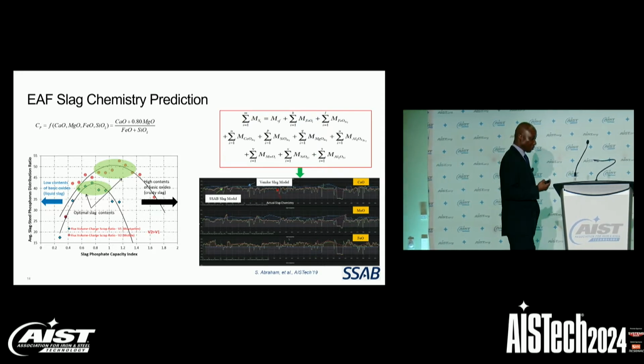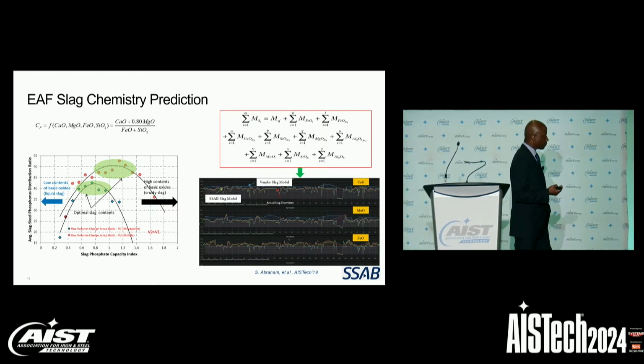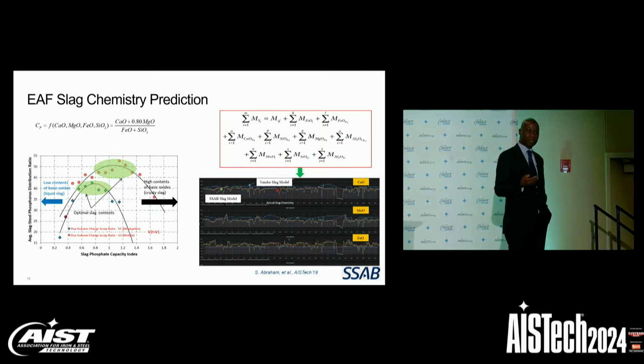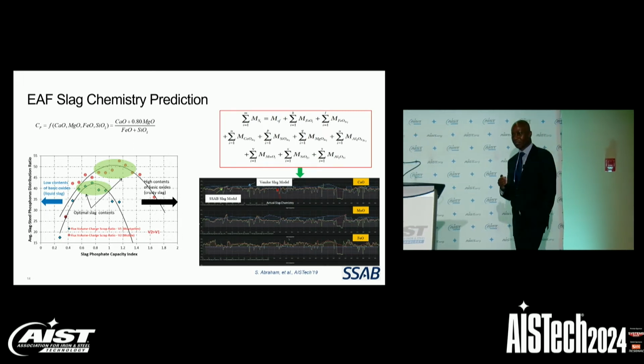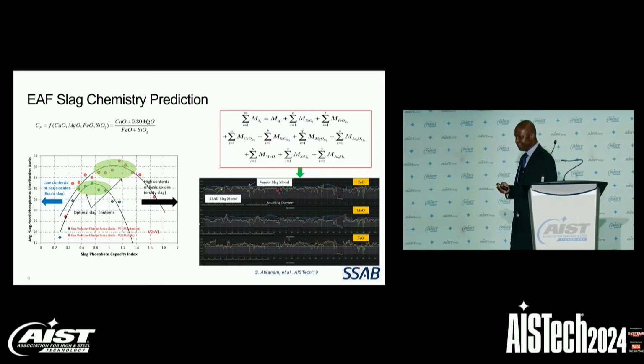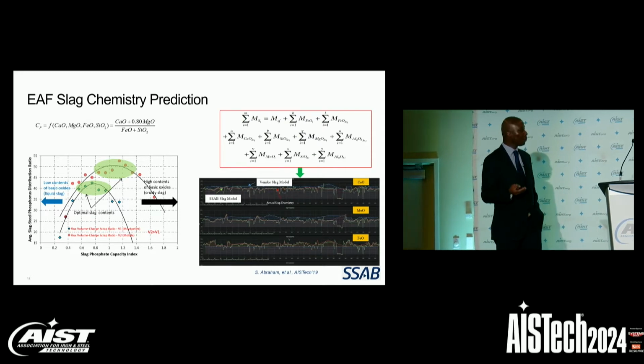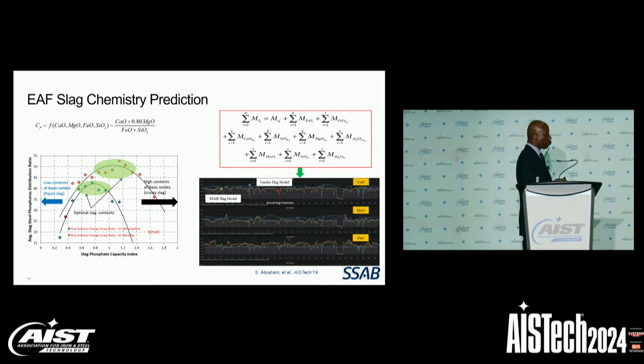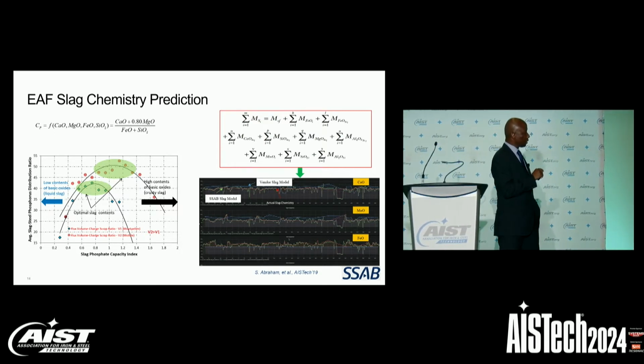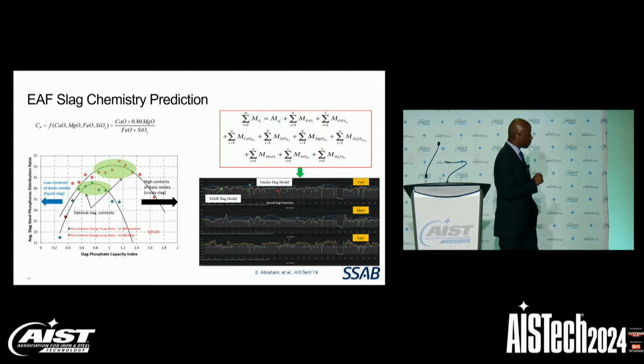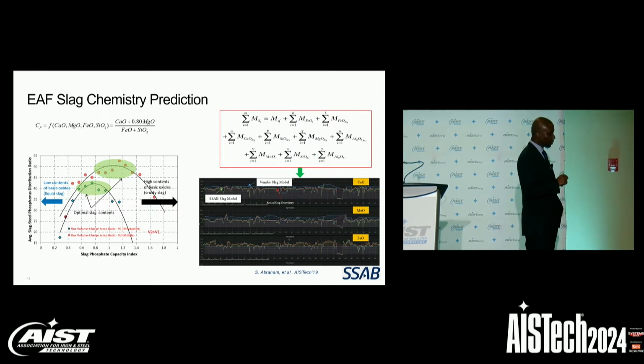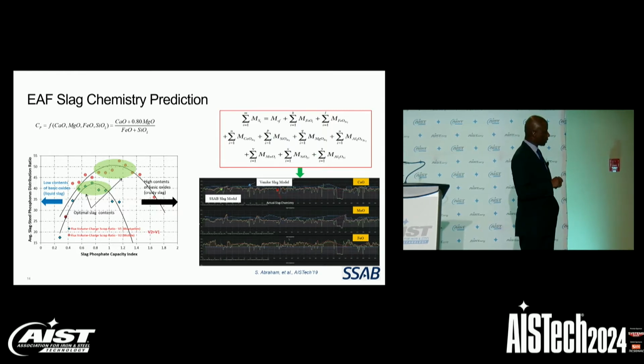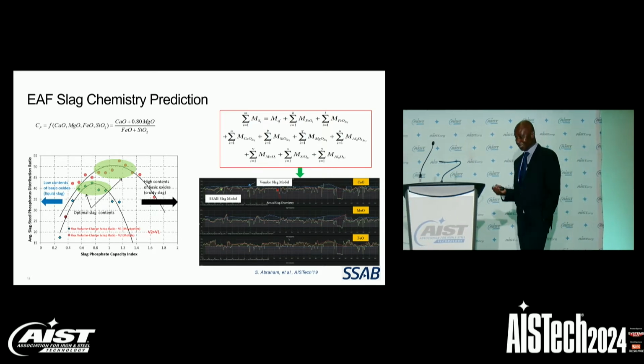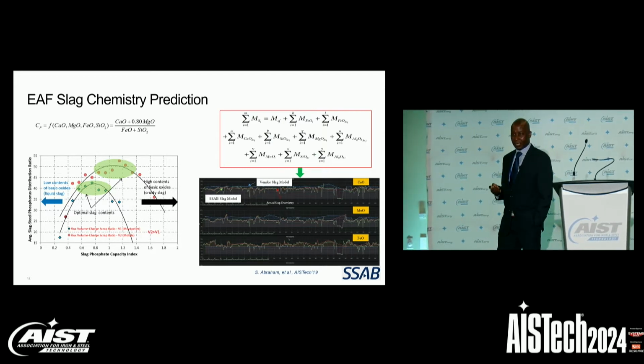By studying the historical data on slag composition and steel chemistry, we determined that the capacity of the slag to absorb phosphorus from the steel is highest when its concentration is in the optimal range. Using mass balance analysis of the fluxes that were added to the electric arc furnace during scrap melting, and in conjunction with our sub-model on oxidation kinetics, we developed a slag model to predict the slag chemistry. The green curve represents the predicted slag chemistry, and the red curve represents the measured slag chemistry. As you can see, there is very good agreement between the predicted and the measured slag chemistry. Now, operators can use the model as a reference to adjust the slag chemistry as appropriate.